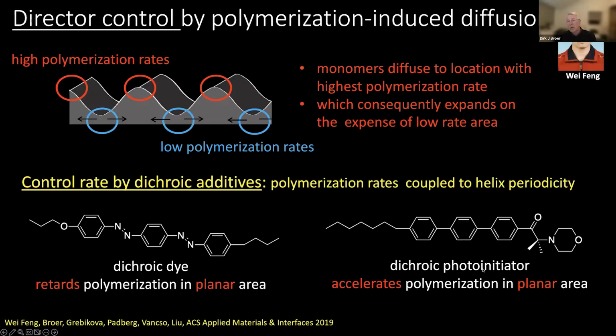On the other hand, you can use a dichroic photoinitiator, a photoinitiator which also aligns with the liquid crystal. And now in the planar state, it starts to absorb more light than in the area where they are perpendicular. So you create more reactive particles, free radicals in these systems. So now we have a higher polymerization rate in the planar areas in comparison with the perpendicular areas. So diffusion will take place to the planar areas. So that is the game that we are playing here.